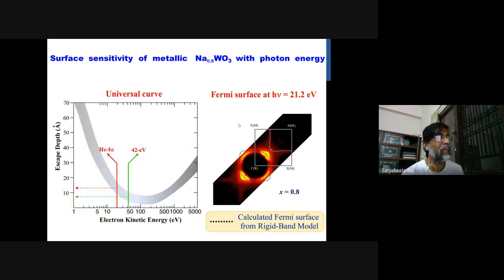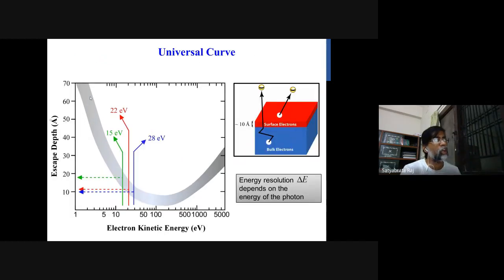So you can probe a metallic sample, the surface and the bulk. How can you do that? This is called the universal curve. If you choose your incident photon energy lower than, let's say, maybe 50, then as you go to lower energy, this will become more bulk sensitive.